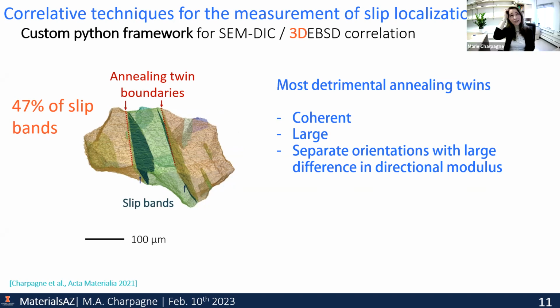So how we're interpreting this is essentially this twin boundary separates crystals that have very high difference in elastic modulus. So from finite element analysis, very simply, if you mesh this grain and strain it, you would see that there is a high stress concentration near the twin boundary. What we don't understand is why the slip band forms close, but still at a given distance from the annealing twin boundary. This we cannot understand just yet.